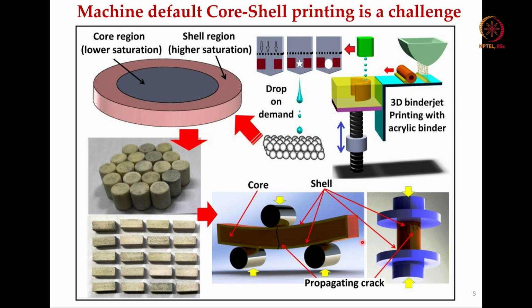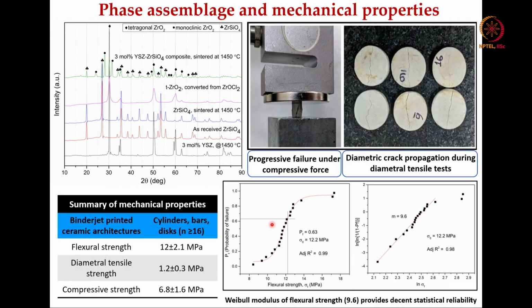So, with this machine default core shell printing, one has to bypass it, otherwise what we found is that there is no way you can improve the quality and the properties of the as-printed constructs, particularly in the case of zirconia. And you can see that a large number of cylindrical and rectangular cross section samples were binder jet 3D printed and also sintered, and thereafter they were fractured, either under compression, like the cylindrical cross section samples, whereas rectangular cross section samples were fractured under a 3-point bending configuration. And you can see how these cracks originate from the tensile face, that is the face opposite to the loading face, and from the tensile face cracks generate and then propagate, leading to the failure, right.